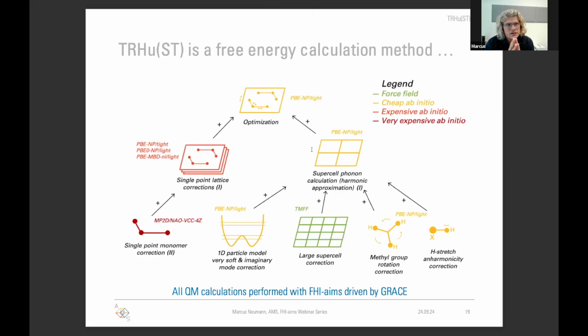So we call this TRUST method a composite method. A composite means that it actually consists of many different calculations, which all have to be acted out together to compensate for each other's shortcomings, so that in the end you get something relatively accurate. And if I quickly talk you through, like in the original method, we optimize crystal structures with relatively inexpensive ab initio. Then, and here I'm in the left branch, we do single point corrections on those optimized structures for certain effects. For instance, light to tight basis set, PBE to PBE0 functional, our own van der Waals to the MBD van der Waals. And so we do single point corrections on the crystal structures.